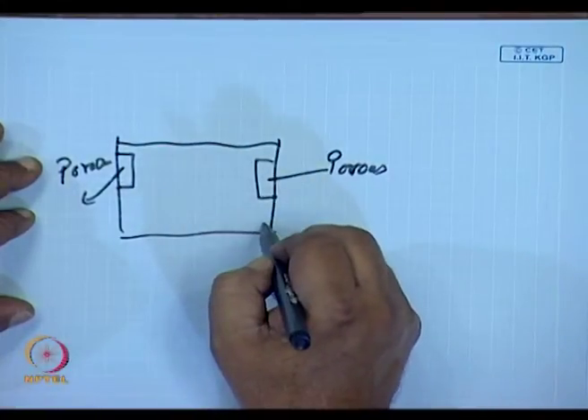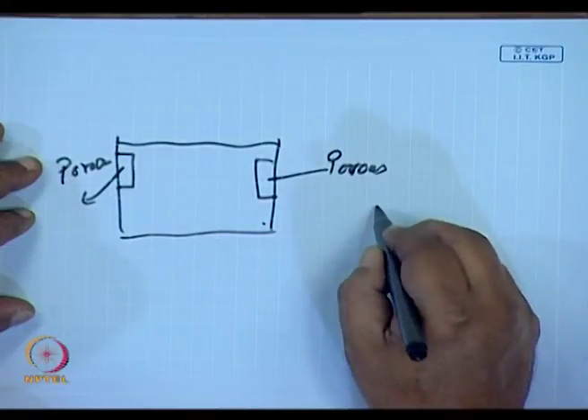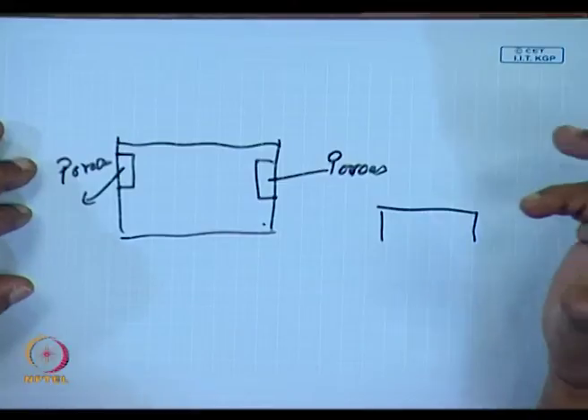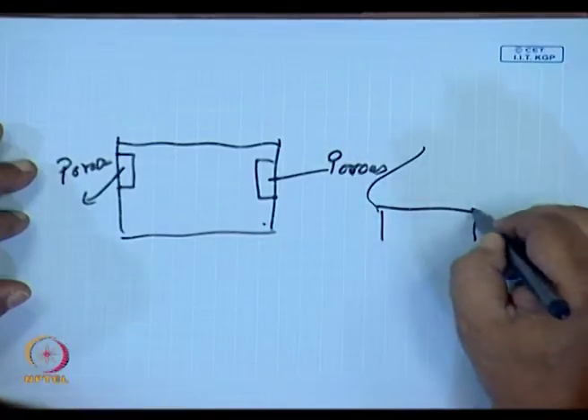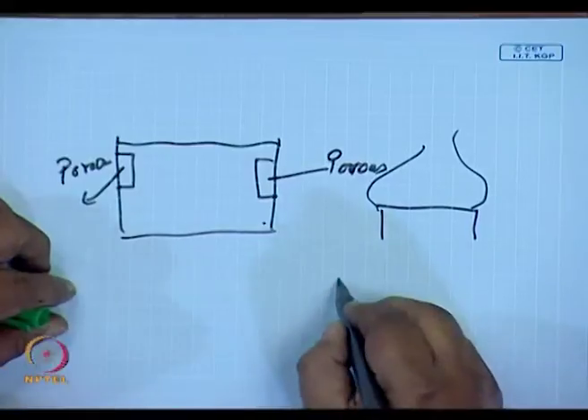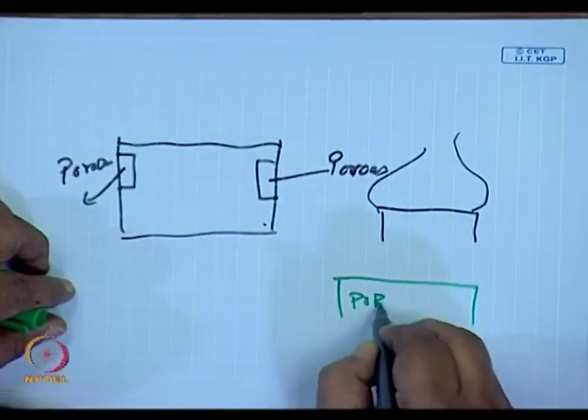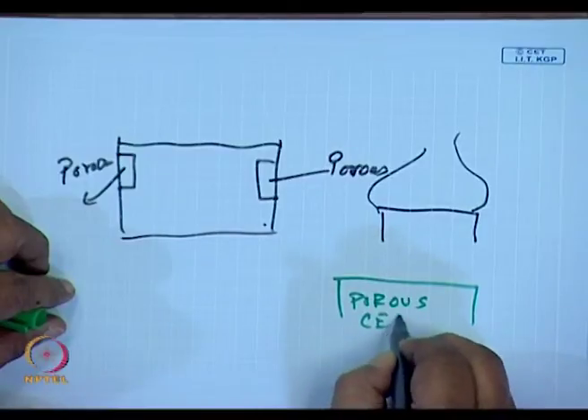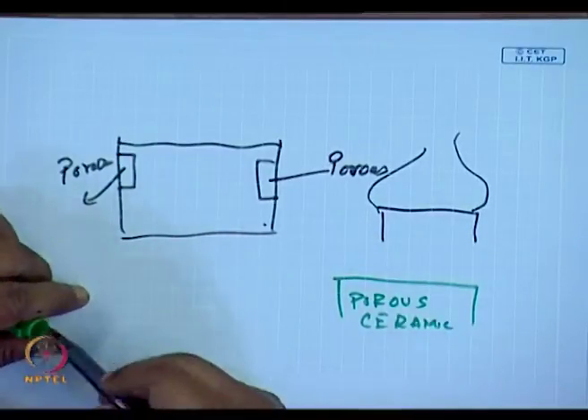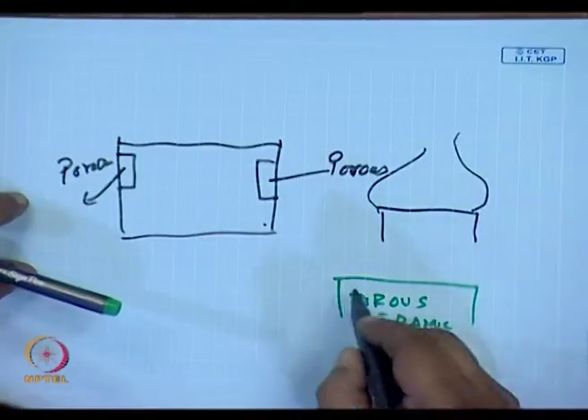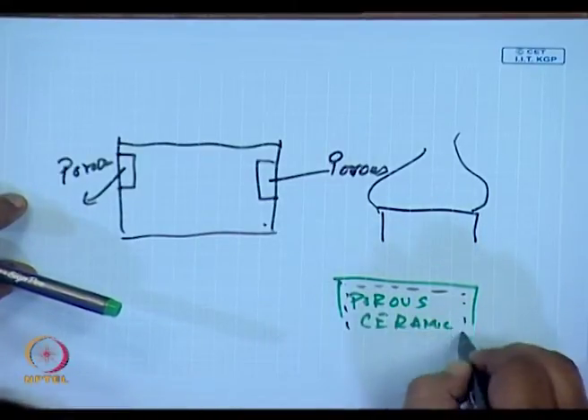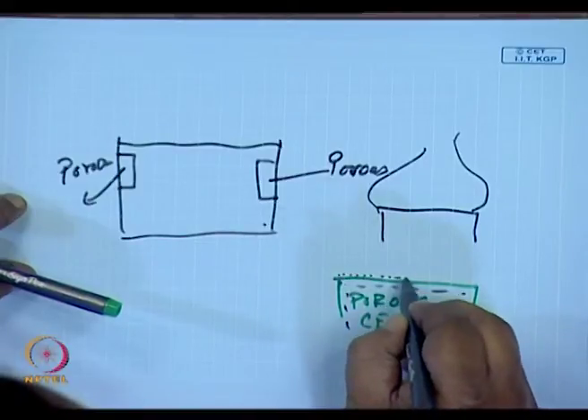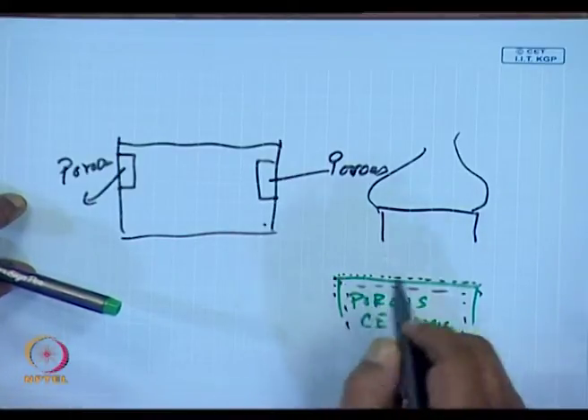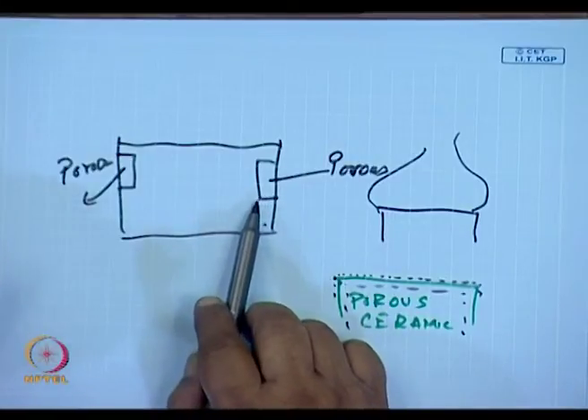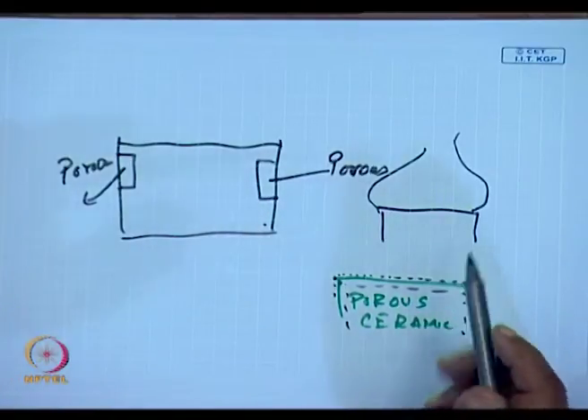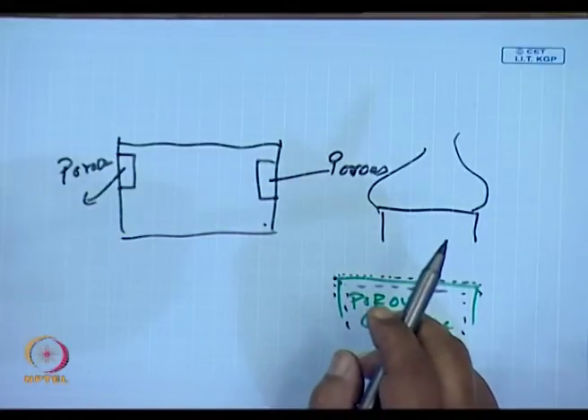Right in the sides. From the gas burner, no flame comes out. In your house, in the gas burner, there is always flame coming out. But in these porous ceramic burners, there is just no flame, because of the very fine pores here, they burn right over here. And once these porous burners are embedded in the melt, they just burn, and heat transfer is very high.